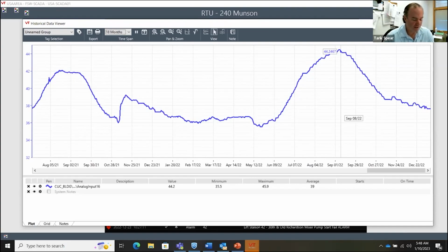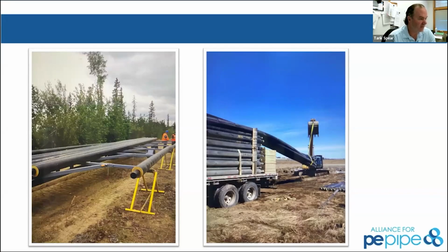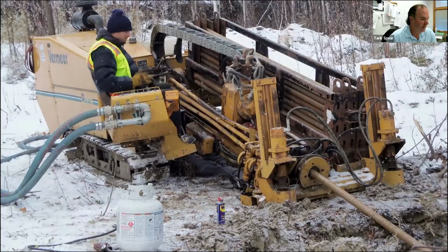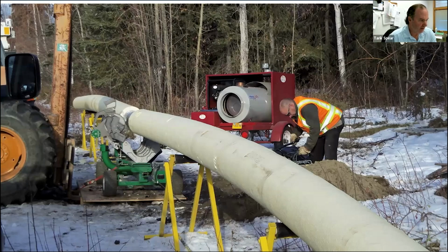Labor: construction season in Alaska tends to run from March to October. This is probably an October picture. We have our heater set up, like Jim was explaining. This is an 8-inch HDPE main. We've had the luxury of a contractor here in Fairbanks that does polyurethane foam. They built a 40-foot lathe, so they can place this 40-foot HDPE on the lathe and uniformly spray on the exact measurement of insulation we want. If we want 1 inch, the pipe would come with 1 inch of insulation, all dependent on how the water model and thermal loss calculations turn out on a loop and the speed at which it's going to lose its heat.